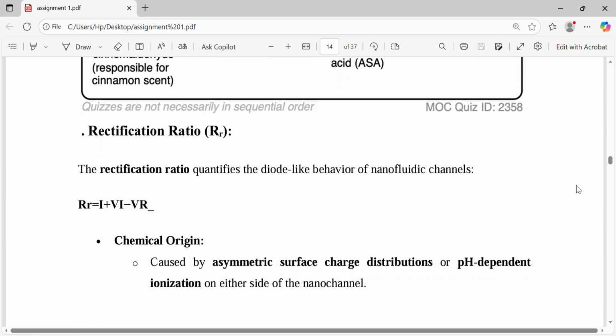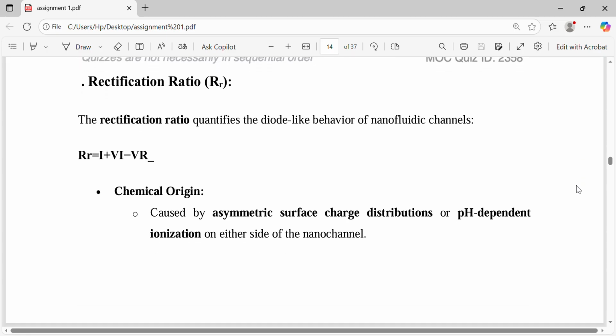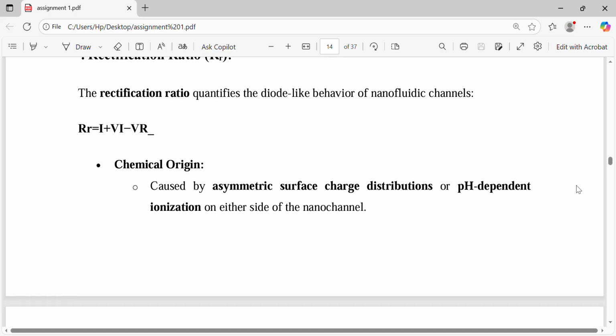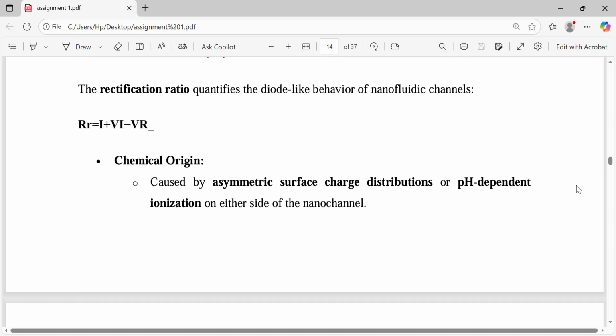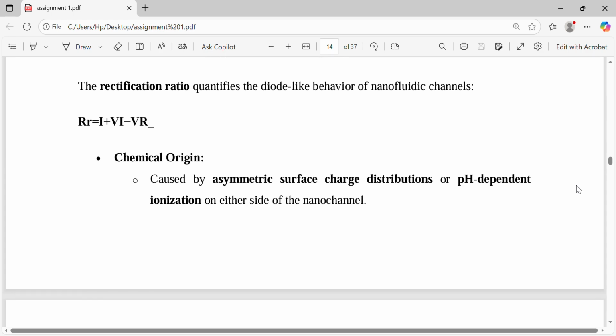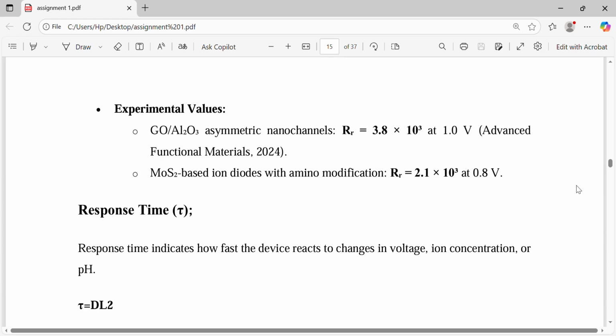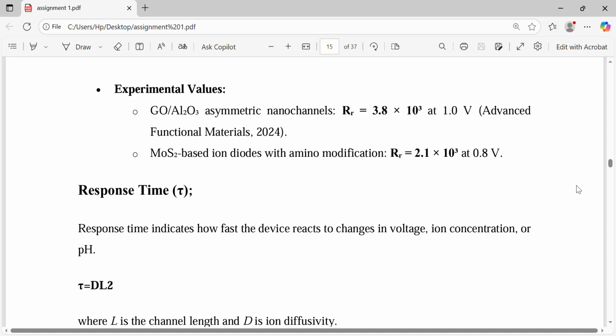Rectification ratio. The rectification ratio quantifies the diode-like behavior of nanofluidic channels. RR is equal to 1 plus Vi minus Vr. Chemical origin: caused by asymmetric surface charge distribution or pH-dependent ionization on either side of the nanochannel. Experimental values: GO over Al2O3 asymmetric nanochannels; MoS2-based diodes with amino modifications.